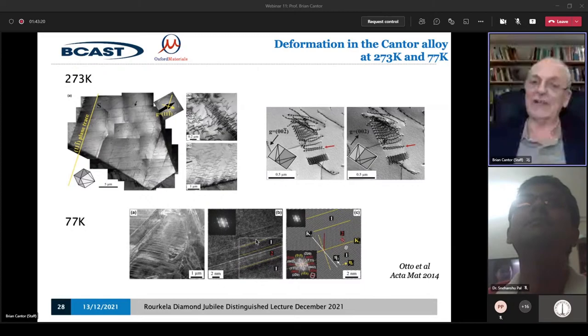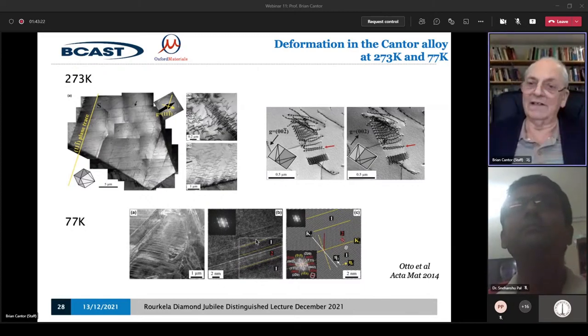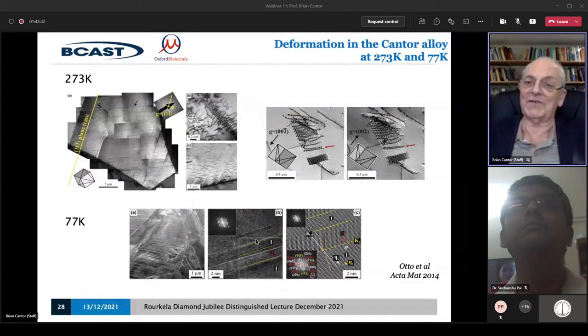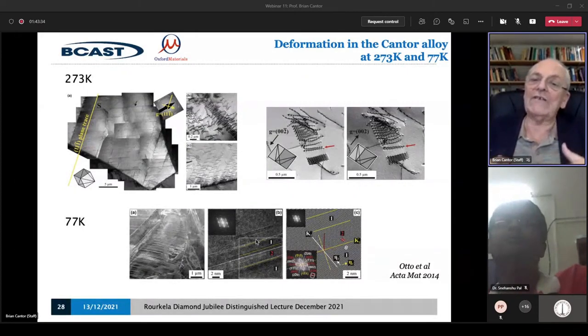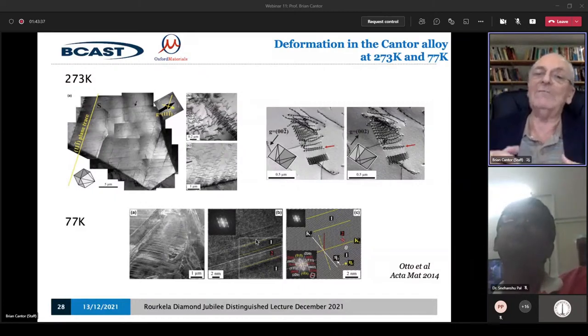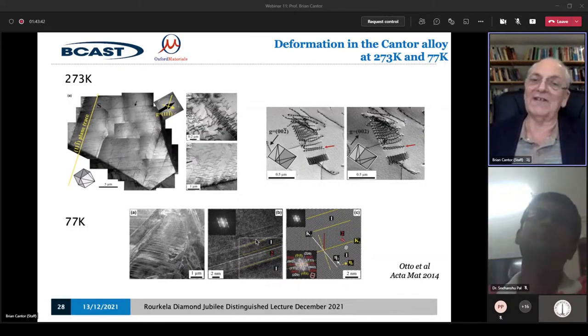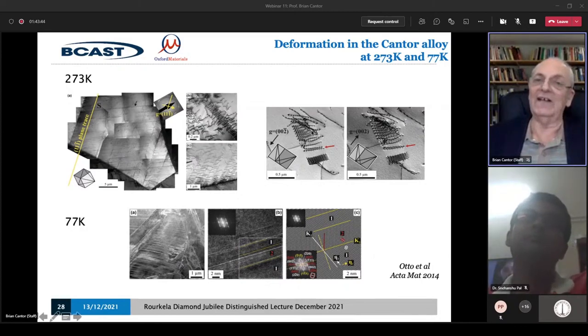TRIP means transformation-induced plasticity, transformation from FCC to HCP, and TWIP means twinning-induced plasticity. Those are the two effects I've just talked about. So you can get extra deformation modes, which give you even more ductility and fracture resistance, because not only do you have the normal FCC dislocation behavior, the dislocation ductility, you also get the twinning and the transformation plasticity. And you can tailor all of that, and people have been doing precisely that.